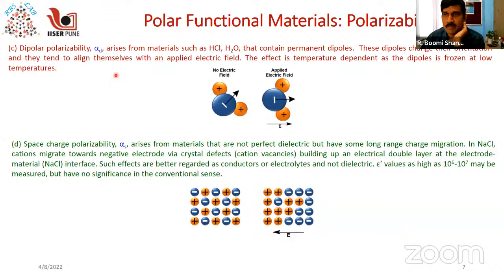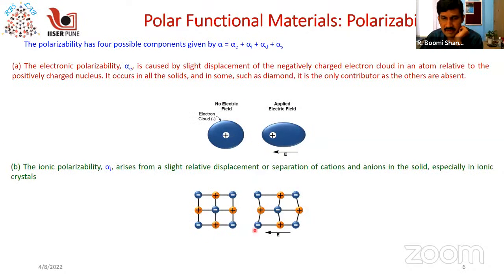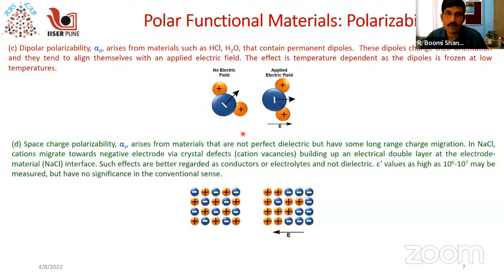In this dipolar polarizability, the dipoles in these molecules change their orientation and tend to align themselves during the application of an electric field. In the absence of an electric field, these molecules will have a random orientation, and then once you apply an electric field, the dipoles orient along the direction of the applied electric field. So these are called dipolar polarizability. If you compare the ionic polarizability and dipolar polarizability, the difference is that in ionic polarizability, the positive and negatively charged ions will migrate, whereas in dipolar polarizability, the entire molecule shifts its orientation. So this is a displacement of the entire molecule in the system.